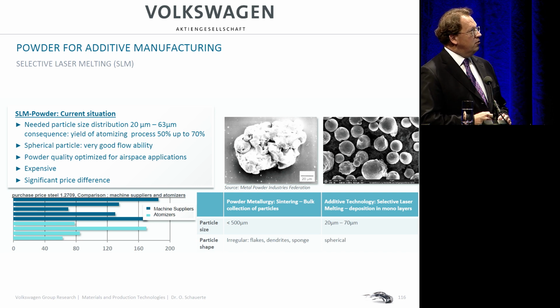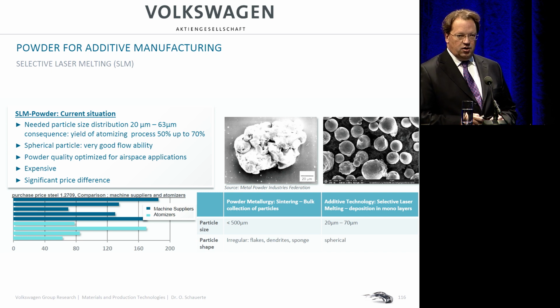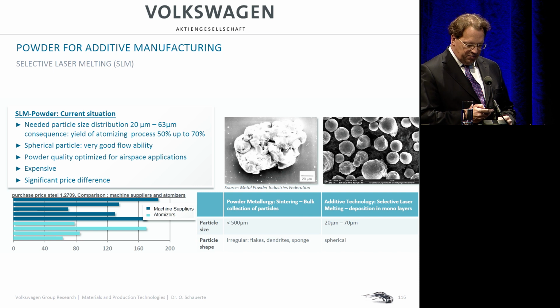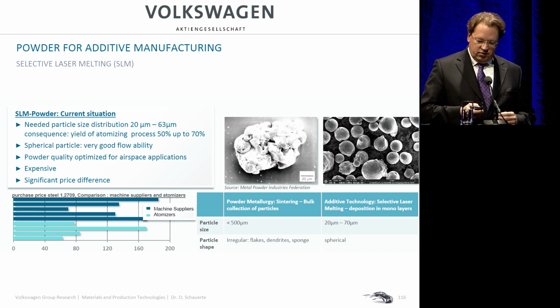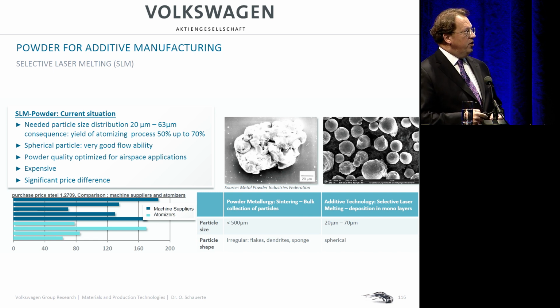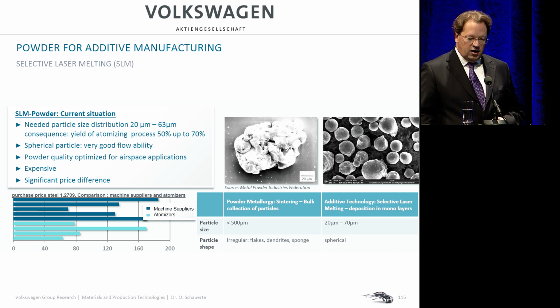If you compare this to classical sintering processes or press processes, as you have in the green part, there you accept parts with a complicated shape, which are flaky, which have dendrites, and you are even happy if they have an irregular shape so that they stick together very well in the compressing process. The high demands for the powder we use for 3D metal result in